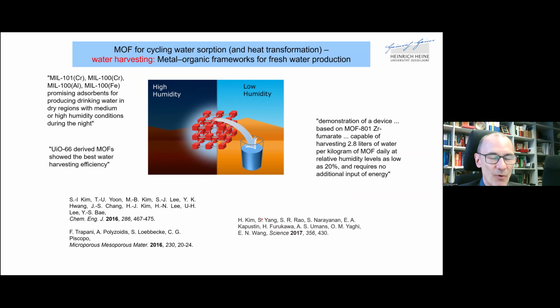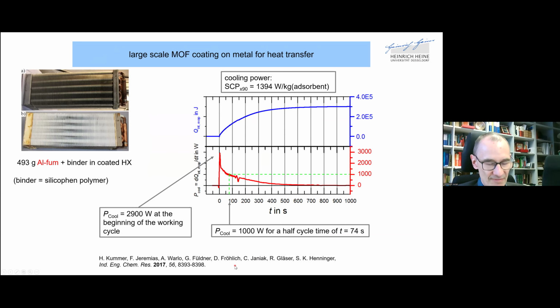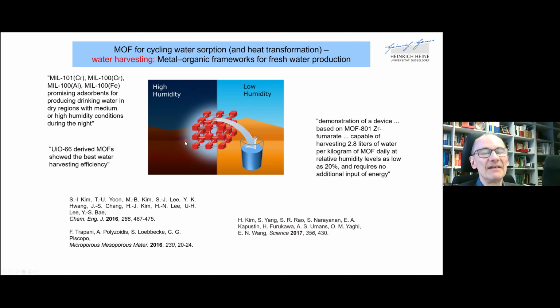And before I now come to my final conclusions, let me point out some other aspects which go along with water absorption in MOFs, and that is primarily nowadays from the group of Omar Yaghi, water harvesting. So I only show you this one single picture here, that MOFs can take up water, are stable and so on, and especially can take up water at low humidity, as I have shown. So at a low relative humidity of less than 0.3.